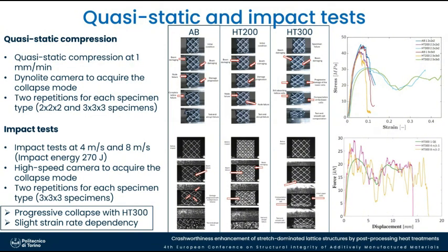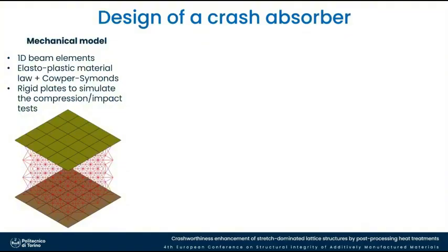These results, however, show that at 200 degrees, we still get basically a brittle behavior. At 300 degrees, we can get instead a very progressive collapse and a bending-dominated behavior. So we identified the proper heat treatment for our application.